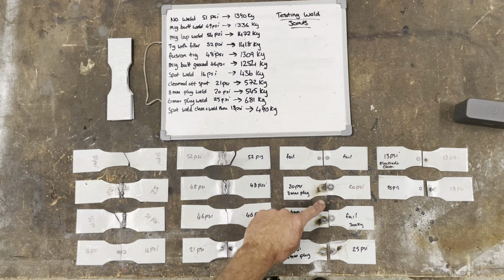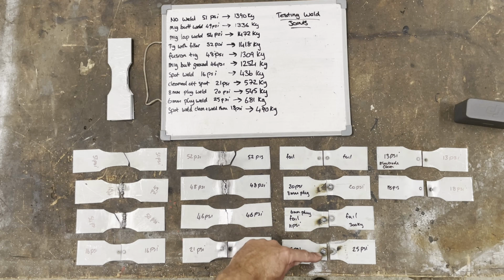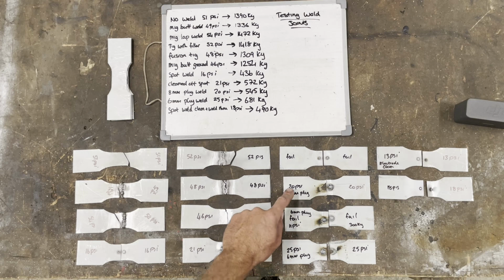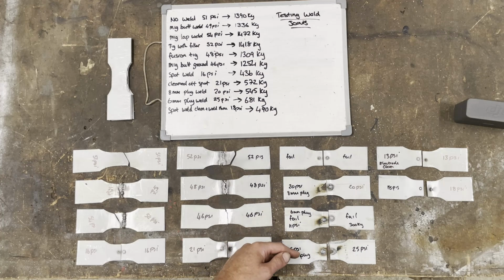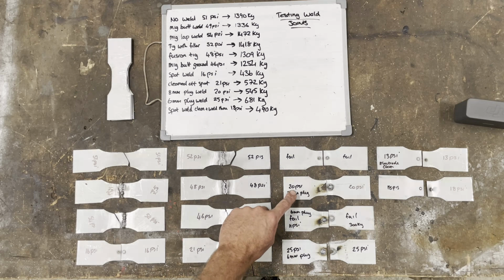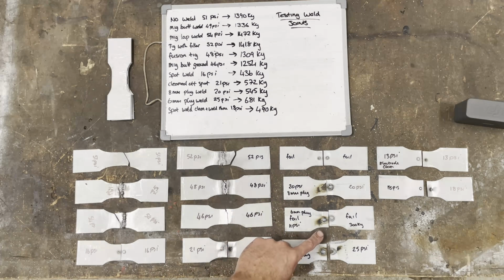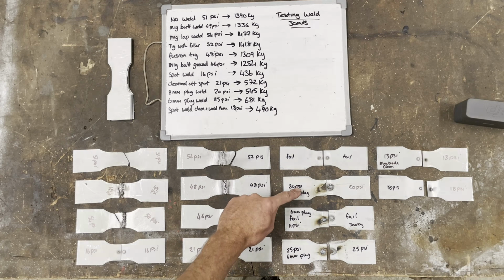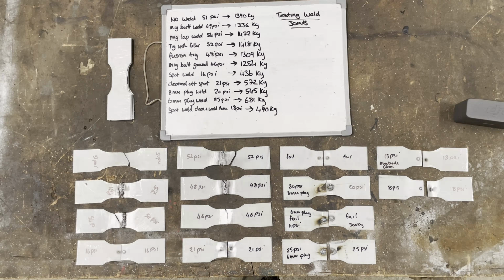Plug welding I expected to be stronger than it was. Not much difference to the spot welding really. Slightly better, but not a big difference. Also, an 8mm hole for a plug weld is slightly weaker than a 6mm. 6mm 25 psi, 8mm 20 psi, but the 6mm is a bit inconsistent with getting it to weld at all. So you've got to be careful with that. So I'd favour the 8mm and get the reliability there.